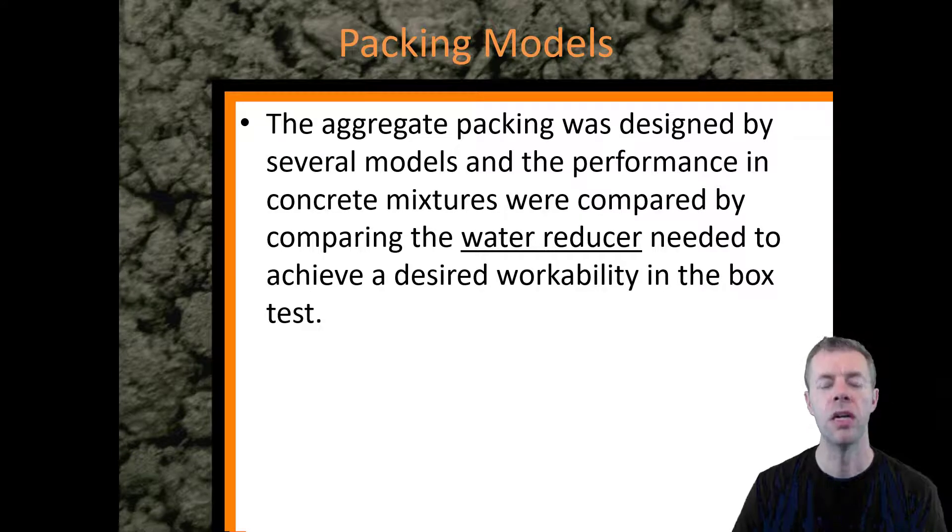Let's talk about packing models. Now these are idealistic models where you take the aggregates and you usually assume that they're spherical, and you talk about how they should pack together. There's lots of different theories out there. We're going to evaluate the models by looking at how they would predict different concrete mixtures would perform. But we're going to compare the concrete mixtures by the amount of water reducer needed to have a desirable workability in a test called the box test that's used for concrete pavements. Let me show you what I mean.